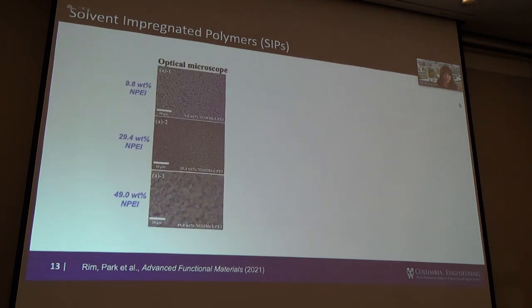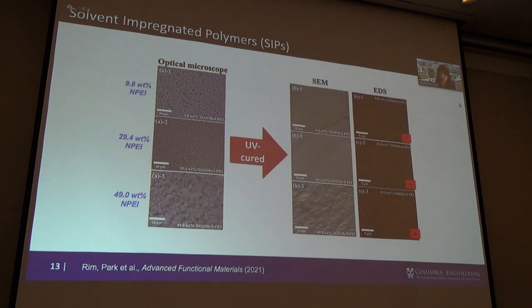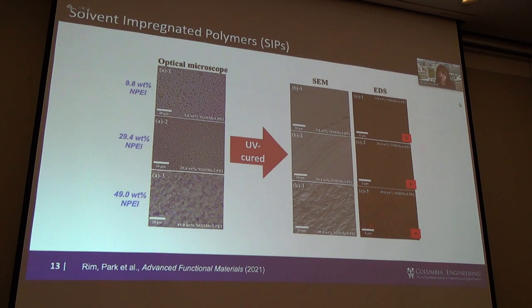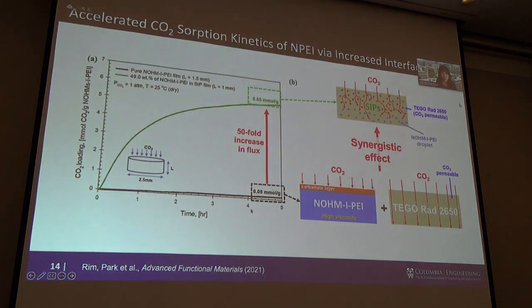If you look here, the first picture shows the optical microscope image of 10% all the way to 49% of NOHMs loading into our Tegorad, which is a UV curable polymer. And once you cure the polymer, it looks like this. If you look at the last column, it's showing the nitrogen mapping, which follows where the NOHMs are. And obviously, the NOHMs are well distributed in the system, and we were able to get even an order of magnitude improvement in how fast we can capture CO2 using SIPs. Knowing this, we were super excited, and this is the data showing a 50-fold increase in CO2 capture kinetics.